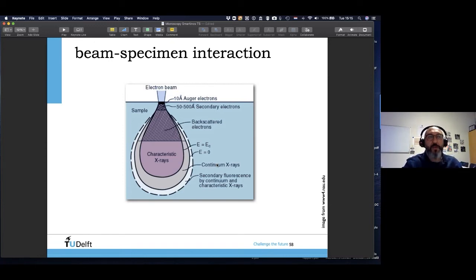Why is this important? Because you might be interested in the microanalysis of a super small area in your specimen. Let's say you generated some self-healing products, but they are really tiny. If you choose to have a very high accelerating voltage, you might think you're analyzing your tiny phase, but actually you are analyzing a huge volume because you chose an unnecessarily high accelerating voltage. So you should be smart and try to lower your accelerating voltage so that your interaction volume will be small and you will get realistic information from your surface, from your spot analysis. This interaction volume is really an important thing, and I'm observing people make a lot of mistakes by not paying attention to the accelerating voltage and interaction volume.